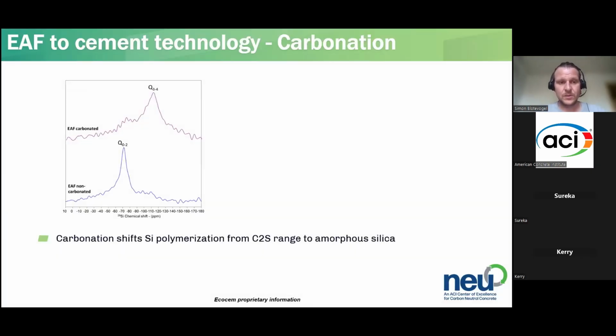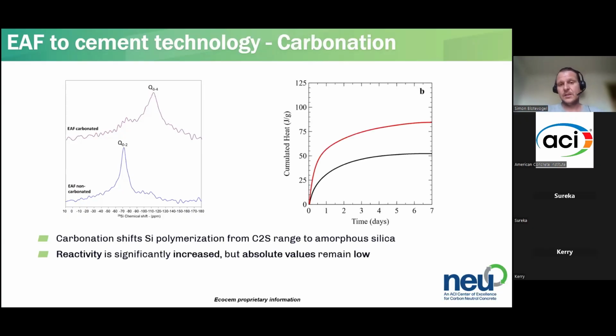Just as an illustration, we've done some work on this. What happens is if you take the non-carbonated EAFs, like here, this is a 29 silicon NMR spectrum. Your silicon coordination is in the range of Q0 to Q2 species, so relatively non-polymerized. And after carbonation, this shifts to the range of amorphous silica Q3 to Q4. So you actually produce an amorphous silicate, and you can see in the heat flow, in the accumulated heat of a R3 test, that between, in black, the uncarbonated slag and the carbonated slag here, there's a clear increase. You can also note that the increase is not as good as for granulation, but still there remains clearly a benefit in this method.